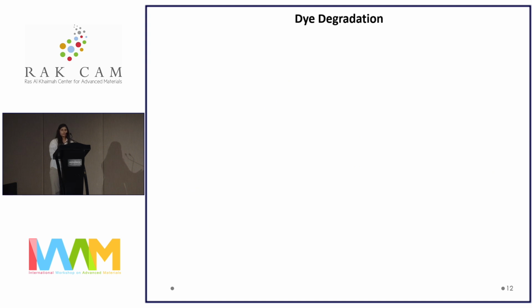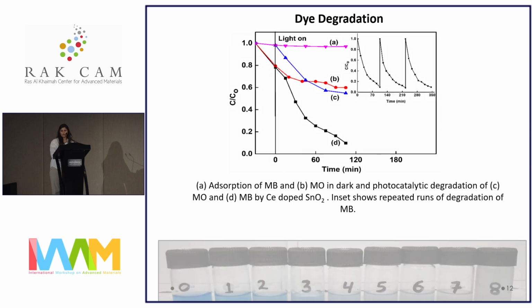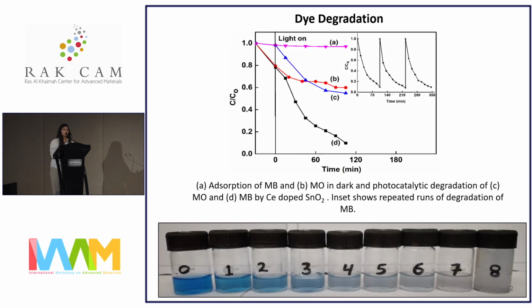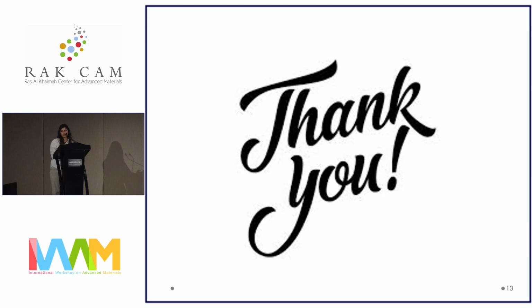Since nitrogen-fluorine co-doped SnO2 behaved as a photocatalyst for photocatalytic water splitting, we tried another experiment on the same principle, and I performed dye degradation with certain dyes, and it was found that it could completely degrade methylene blue dye and 73 and 62% of methyl orange and crystal violet dyes. Thank you.